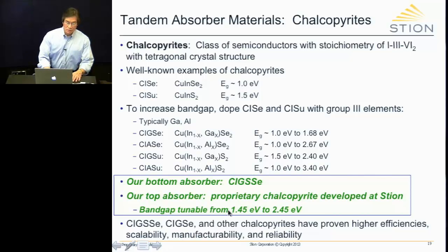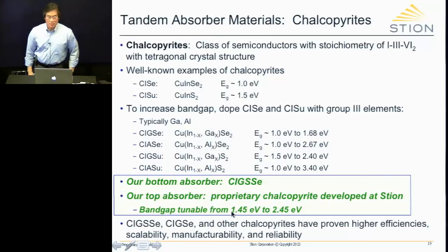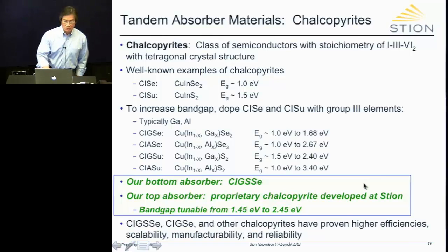For the bottom device, we use copper, indium, gallium, and instead of the diselenide, we replace one of the seleniums with sulfur. So we've made it worse. Instead of a ternary, we have a quaternary material, right? But it turns out that there's a reason for that, and it's too complex to go into at this point, but I'd be glad to answer that after the discussion. Our top absorber, to answer your question, is a proprietary chalcopyrite that we developed in which we can tune the band gap from 1.45 to 2.45 eV. Unfortunately, that's all I can say at this point.